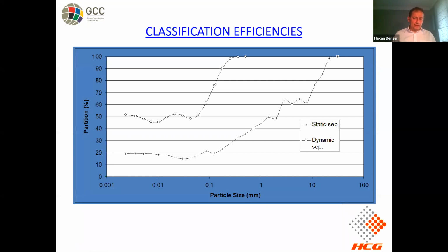Because of that high circulating load ratio, as soon as you reach the fine material, it's extracted by the air classifier from the system, so the product coming out from the vertical roller mill is very steep. Is this a good thing? It's good for the minerals industry because you produce less slime, but it's not good for the cement industry. The cement industry is addressing the side effects of the steep size distribution, especially because of the surface area, the strength value is dropped.